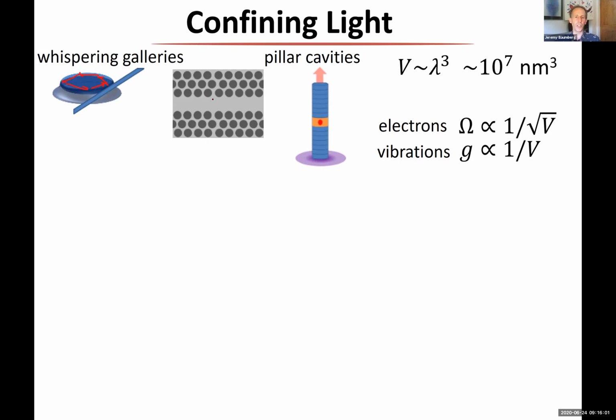And so you have modes which bounce around like this. Or this is a photonic crystal. So in fact, there's a mode in here. You can just see that these holes here in this film have been moved slightly. And there's an optical mode which sits in that slab of semiconducting material. Or you can make cavities like this, which are a bit similar to the ones I showed you, only now you make a small pillar out of it so that the confinement is more tight in the lateral direction here.